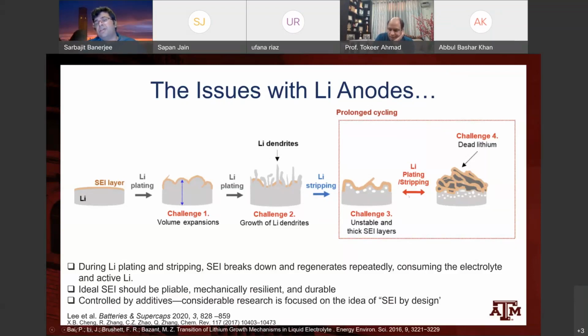So a couple of problems to note. Number one, the lithium metal continuing to react with the electrolyte to form this SEI layer is consuming lithium from the electrolyte without any actual storage. It's just a chemical reaction that is parasitic. Number two, as this reaction continues, regions and dendrite formation is initiated. Regions of lithium essentially get pinched off and become dead lithium. They're surrounded by the SEI, and no longer electrically connected to the lithium metal. Also, another problem that happens as this dead lithium and SEI accumulates, you end up having a very large polarization, a very large buildup of interfacial resistance at this interface, which is also not good for the functioning of the battery.